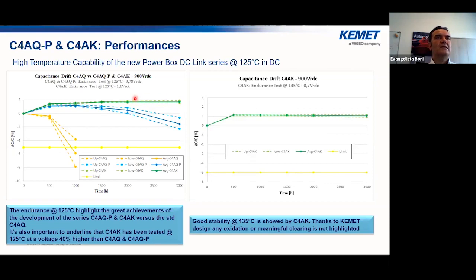And the C4AK is even tested at higher voltages, so a 1.1 rated voltage instead of 0.78. On the right, it's possible to see also the really stable performance of the C4AK at 135 degrees, 0.7 rated voltage.